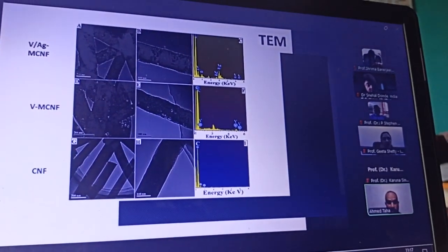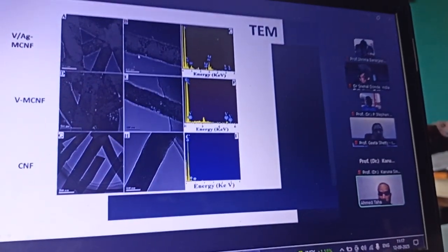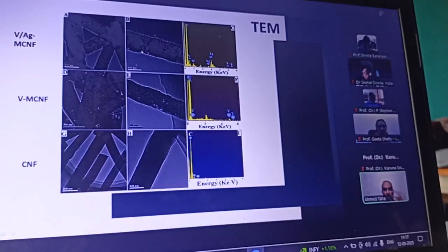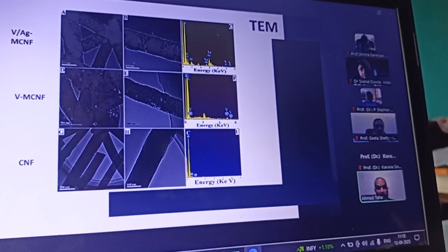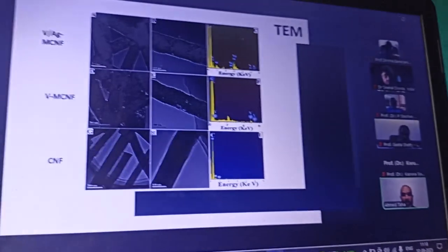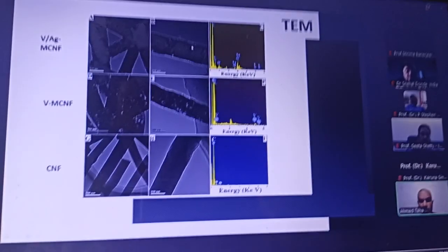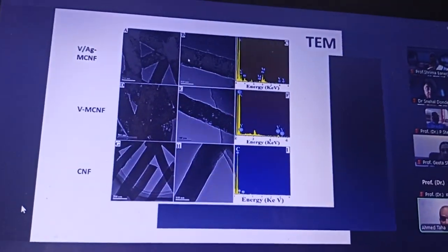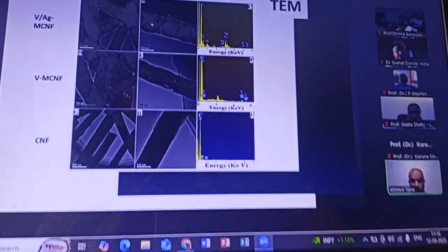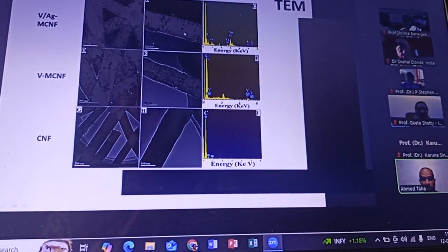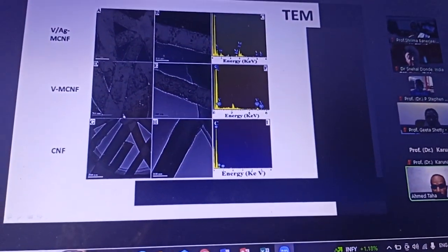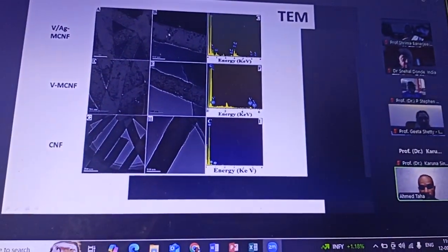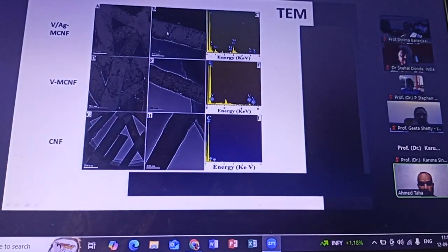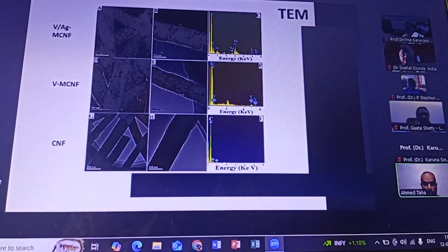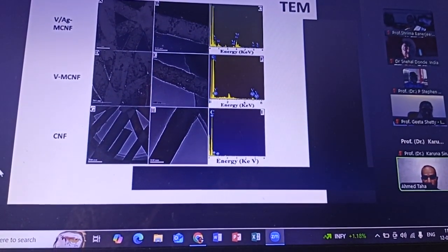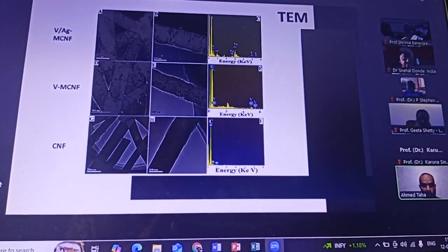And this is under the microscope. You have these white spots. These are the pores created during the thermal treatment. And these black spots are silver dots on the surface. It's very uniform and evenly distributed on the surface. The function of the silver here is to do this disinfection and also to help in the catalytic performance.